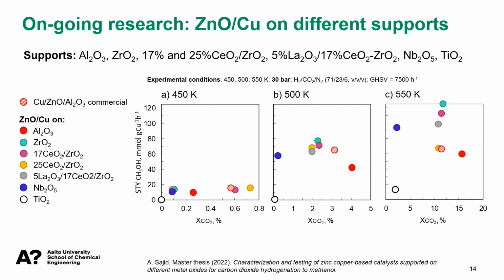So we tested all the supports that you see listed here. What I want to show you here is the methanol production per gram of copper versus the CO2 conversion at three different temperatures. We also included this commercial catalyst that I told you earlier as a reference. So what I want to highlight here is that at the lowest temperature, we observed like similar production rates at different levels of conversion, but still the conversion was very low. But if we go to 500, we start to see how zirconia and also the 17 ceria zirconia, let's say, outperform the commercial catalyst. And this is even more noticeable here at 550 Kelvin. So somehow we produce catalysts that can behave a bit better than the commercial catalyst.